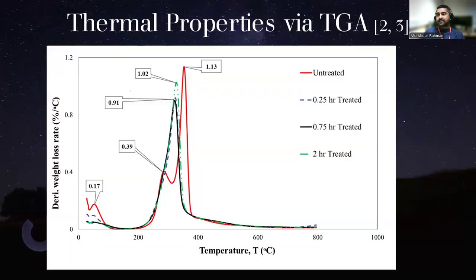Let's see the thermal properties via thermogravimetric analysis, or TGA. I included some of the samples, if not all. The red color is the representation of the untreated fiber. You can see that there are 3 peaks in the red curve. One is at 0.17. That first peak is the dehydration peak.